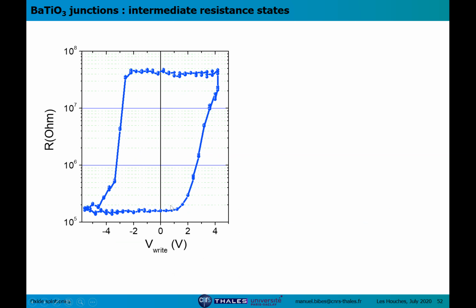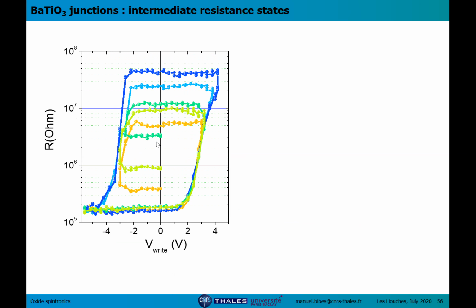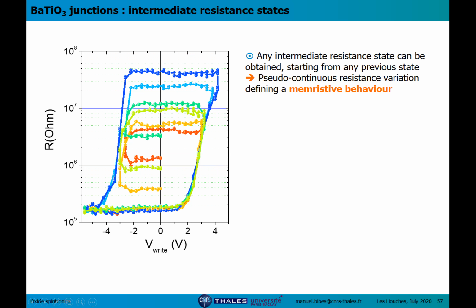And this is maybe better shown on this graph. This is the same kind of curve where we have 2 maximum resistance values. And these are also kind of minor loops where we don't go all the way to the maximum right voltage. We stop before, at maybe 2 volts or 3 volts. And then you see that we can stabilize basically almost any intermediate state. So we have a pseudo-continuous variation of the resistance we can set in these devices. And this defines memristive behavior.